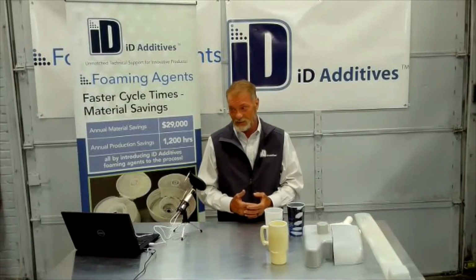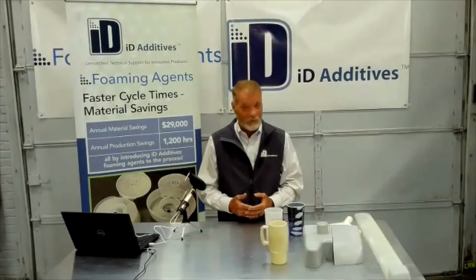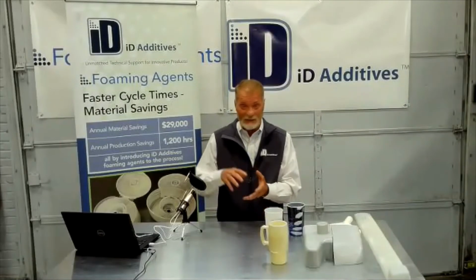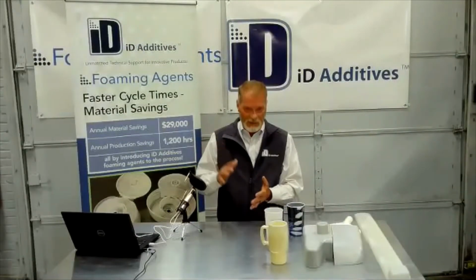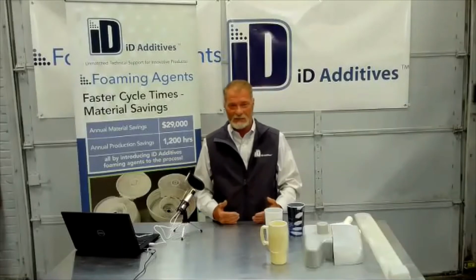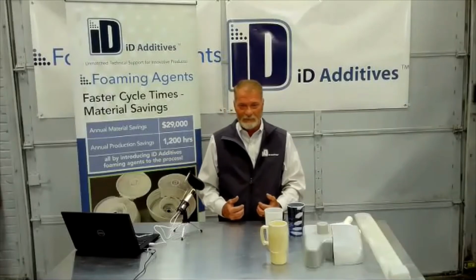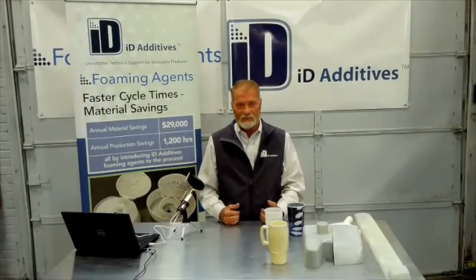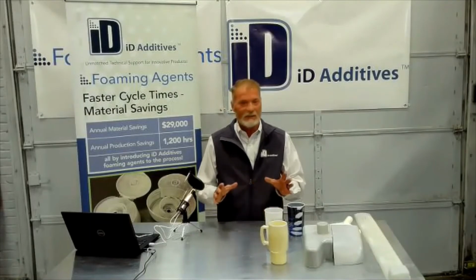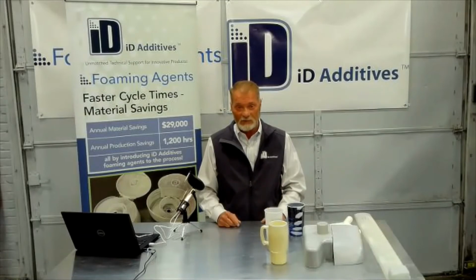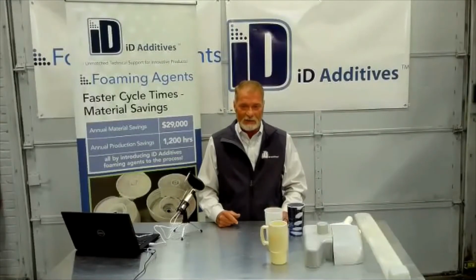I've seen parts that take over 2 weeks to degas before they can paint it, because that gas just takes a long time. Endothermics degas right away. Within minutes, you can spray it. It's degassed pretty much before it even comes out of the mold. So yeah, I think you could do that with an endothermic.